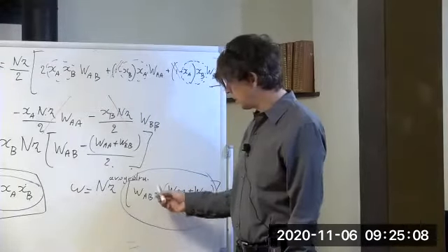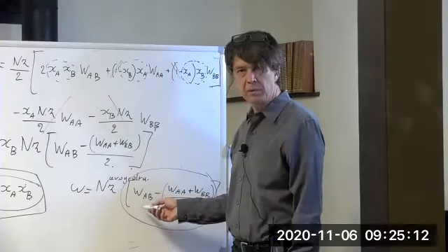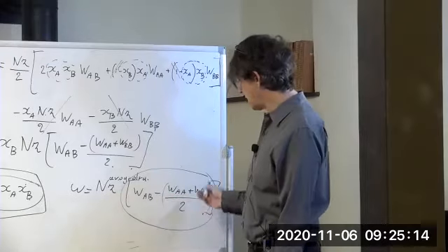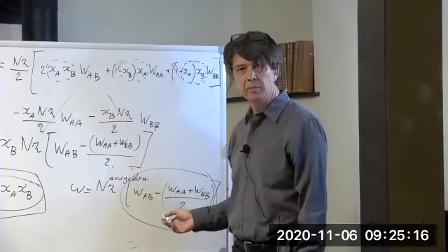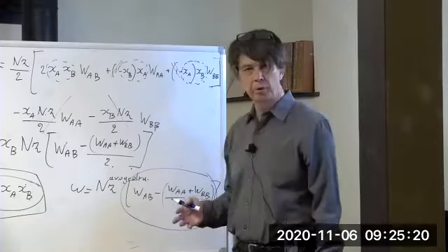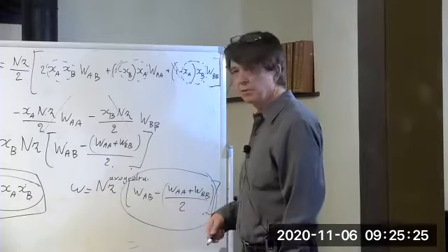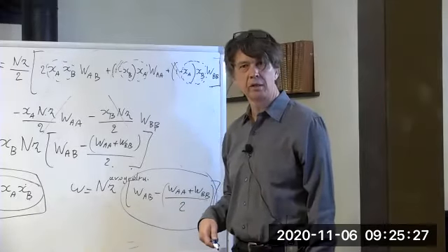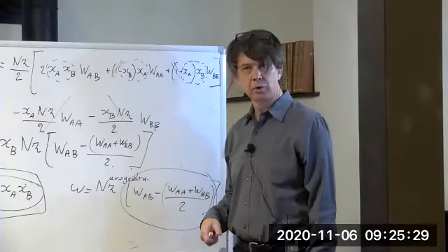It's essentially proportional to the new bonds you make in a mixture, which is the AB bonds, minus the average of the AA and the BB. So the energy of mixing seems to be proportional to the difference between the new bonds and the average of the old bond energies. That's how you could think of it, so that's how you should conceptually try to remember this.